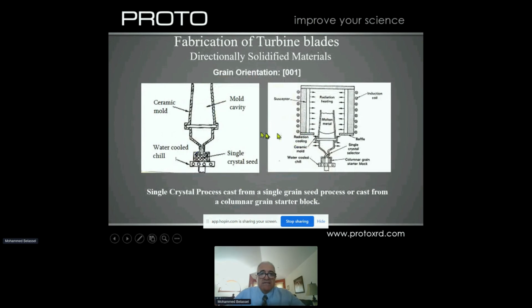How do they make these blades? They make them in ceramic molds, and either use single crystal seeds to start the solidification, or sometimes they use just a chilled plate with a columnar grain structure block. That means it has many grains, and thanks to this kind of corkscrew shaped geometry, they can select only one grain coming out and the rest don't come out. And from that, they can grow the grain in the mold.